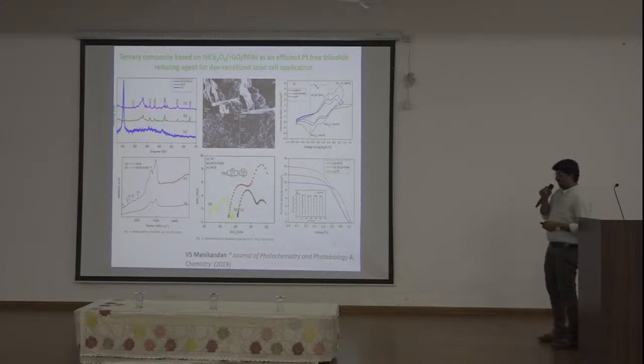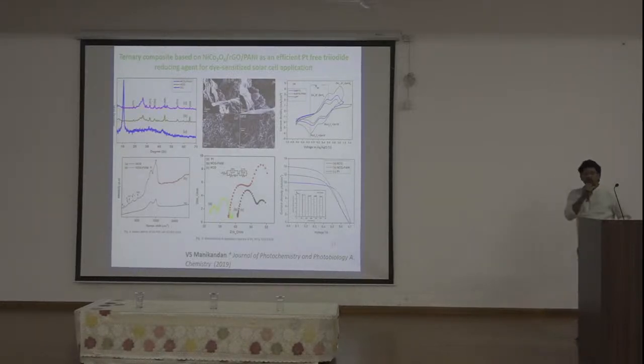Second, we have also tried a ternary nanocomposite, like a nickel cobalt oxide, RGO and PANI-based ternary composite material, to see how it influences the electrochemical behavior as well as the photovoltaic performance. In this basic characterization, we can see the blue color is the graphene oxide peak. After the hydrothermal treatment, the peak is shifted to a higher angle because of the reduction of carboxyl and hydroxyl groups from the GO.